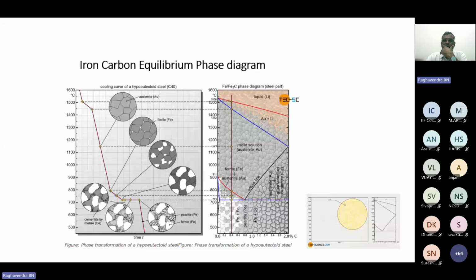Now, for example, if I take 0.4% carbon, see in the iron carbon diagram, up to 2% we call it steel, and more than 2% up to 6.67% we call it cast iron. If you take 0.4% carbon steel, here it is completely liquid, and from this area to this area it is austenite plus liquid. Below this point it is completely solid, and up to this point it is completely austenitic structure. Below this again it is austenite plus ferrite, and below this it is ferrite plus pearlite. This is how the transformation takes place.